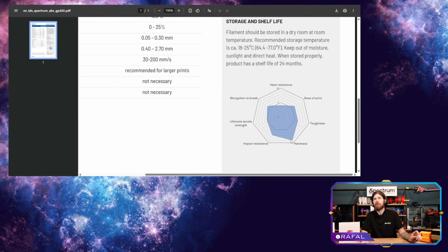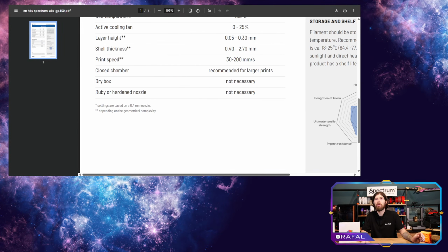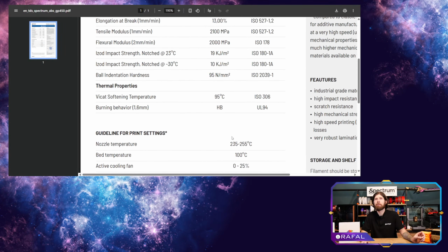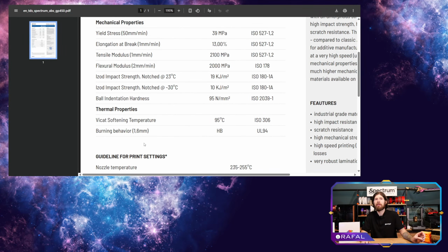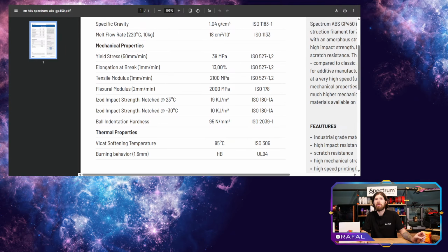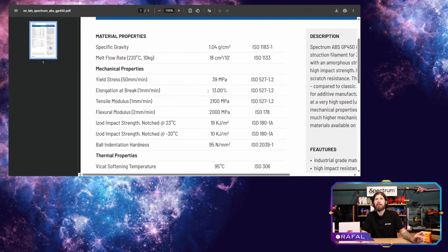It's better. I mean, the hardness is also good compared to ceramic filled, but impact resistance is much higher. Elongation to break is not that bad, and the ultimate tensile strength is a little bit better, but the toughness is a little bit lower. And let's see the... Oh, here is the Vicat softening temperature 95, burning behavior HB, elongation to break 13%.